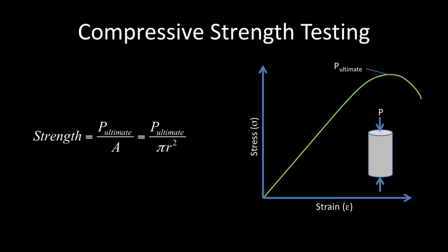The concrete strength is calculated by taking the peak load obtained and then dividing this by the specimen cross-sectional area. This strength will be compared to the strength found from the 4-inch diameter specimens. Generally, the strength found for the 6-inch diameter cylinder will be lower than the average strength found from the 4-inch